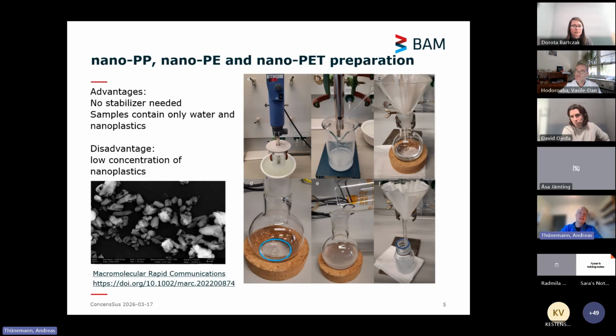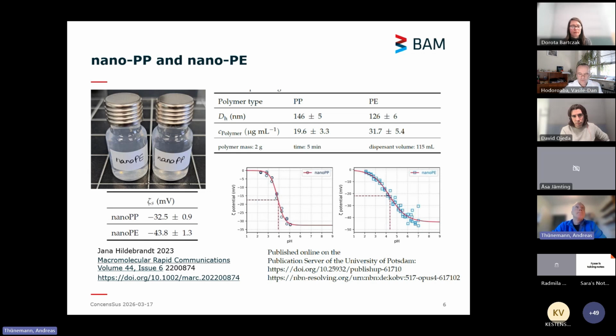The disadvantage is that the concentration of the particles is very low. For example, here you see polyethylene and polypropylene, slightly turbid, so particles are in there. The zeta potential is low: in the case of polypropylene it is about minus 30, and for polyethylene less than minus 40 millivolts. This explains why these particles are stable in solution for 3 years. After some storage time you see some white on top of the suspension, but after vortexing for 30 seconds, the solutions are homogeneous again.